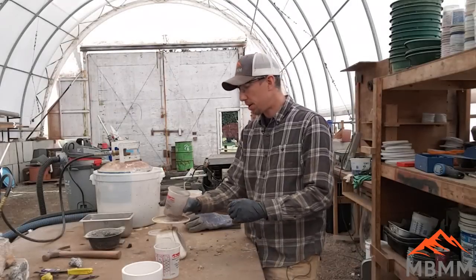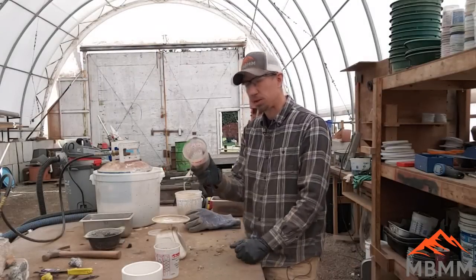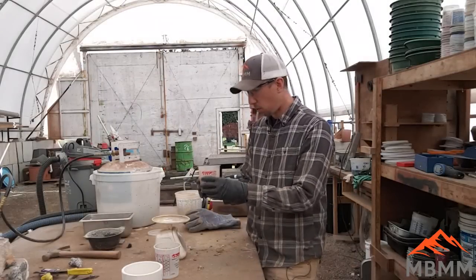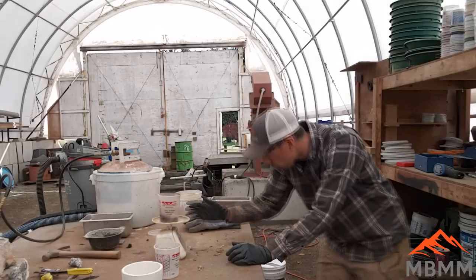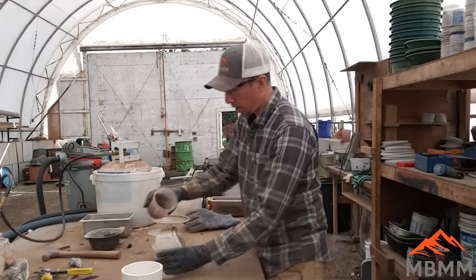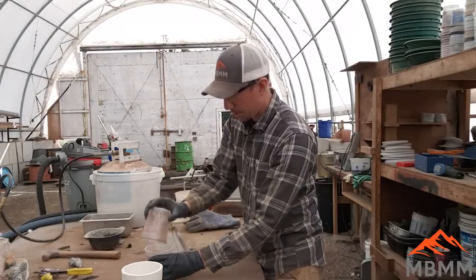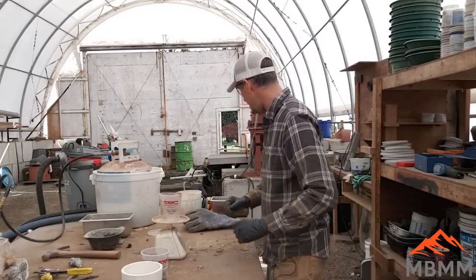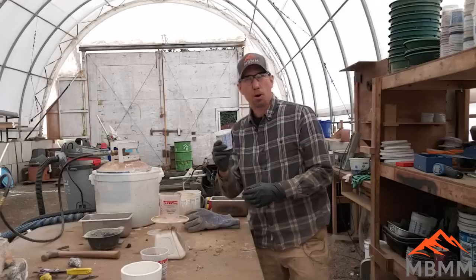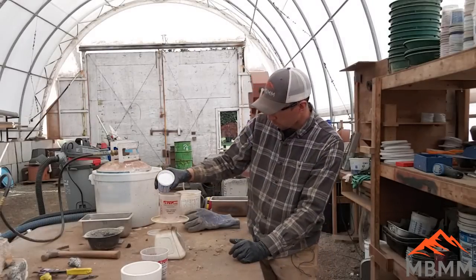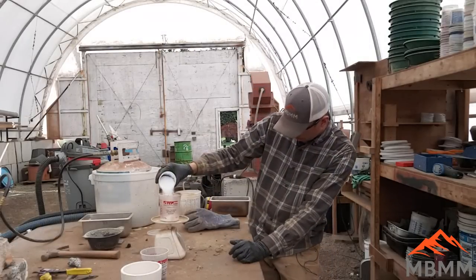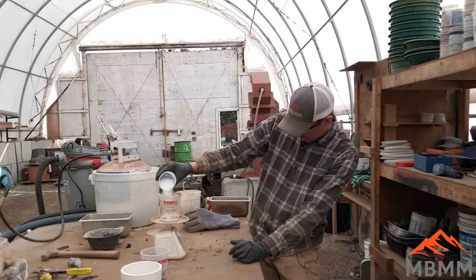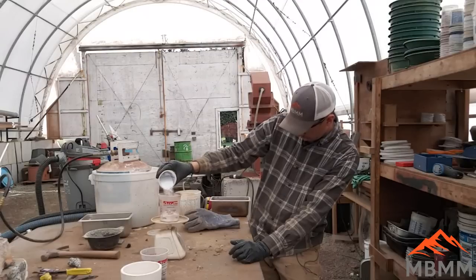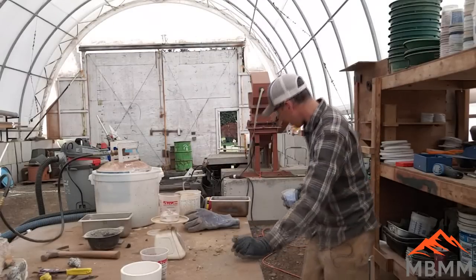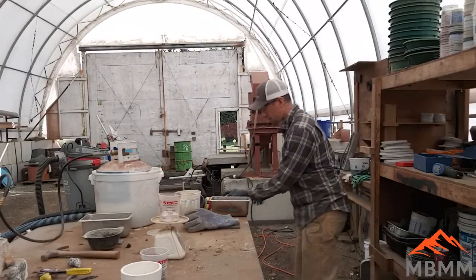All right, so we have our number 1 concentrates from our shaker table. We've dried them out. They weigh just right about 200 grams. So we're going to mix up a flux recipe now so we can smelt those down and get our gold out. So our first component is anhydrous borax, and we're going to use 200 grams of anhydrous borax, the same weight as our material that we want to smelt. So there's 200 grams of anhydrous borax.